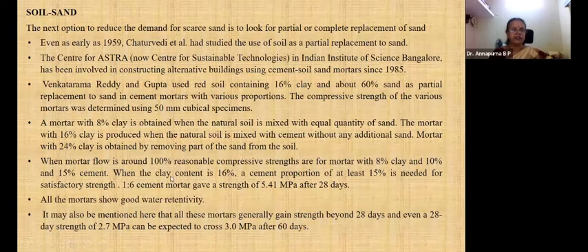So again, when the clay contains 16% proportion, 15% cement is needed. So when you have 16% clay, you have to add 15% cement to get very good strength. This is the mortar they have taken, 1:6 cement mortar, where they have achieved 5.4 megapascal after 28 days.